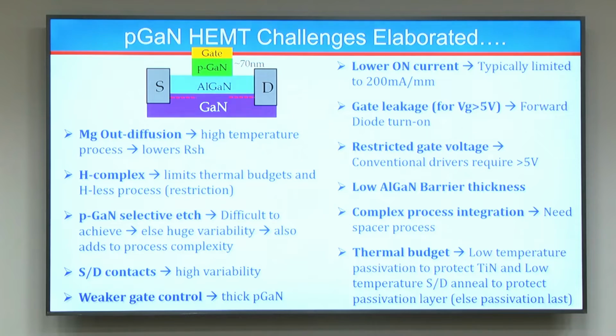Selective etch is what I mentioned earlier, that you cannot do a partial etch, you cannot do an over etch. So you have to develop a process which gives you complete etch of pGaN without removing the AlGaN, right? And in that process, if you have variability across the wafer, you're going to see different kinds of transistors with different performance numbers all across the wafer, right? So this further adds to the complexity.